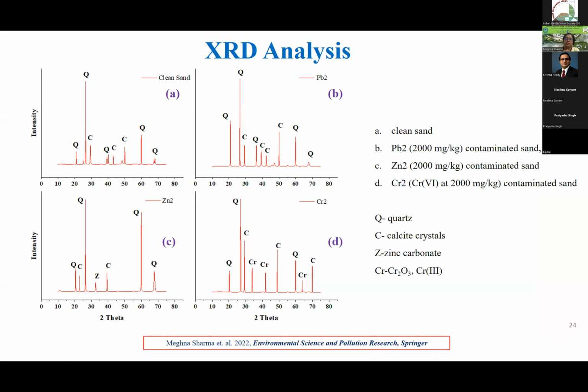Now, through the XRD results, in the clean sand, calcite peaks were observed, and in the lead contaminated sand also, calcite peaks were observed, and in the zinc contaminated sand, zinc carbonate was formed. And in chromium, chromium oxide Cr2O3. Now, the main point which I want you to see here is that I contaminated the soil with chromium 6, which is highly toxic and mobile. Due to this mechanism and process, it converted into chromium 3, which is less toxic and not mobile, immobile. Clear? So that's how this process works in contamination immobilization.